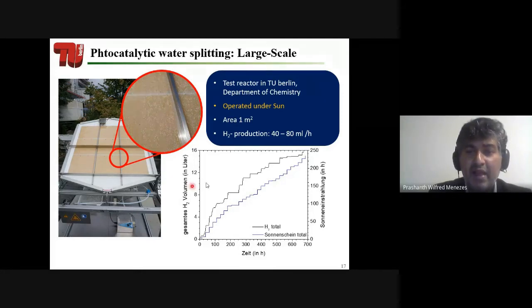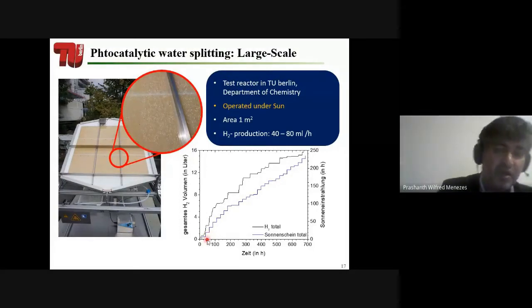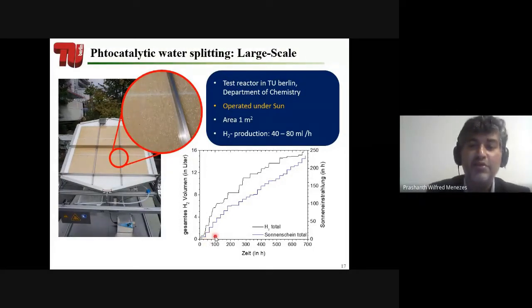We could produce 40 to 80 milliliters of hydrogen per hour, depending on how much sun we have in Germany. This was done in summer. You can see that during the day it goes up, and in the night it is stable, because we do not have any sun in the night. So it doesn't work without sun.